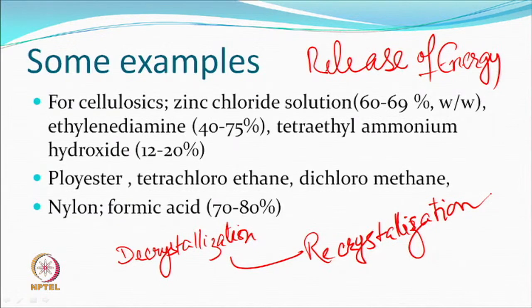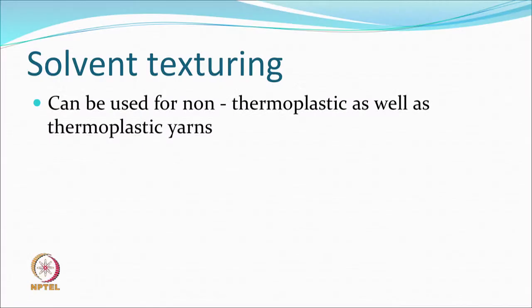If 100 percent concentration dissolves, reduce the concentration and add a non-solvent and you will find it does plasticization more than dissolution. The material must still go through the decrystallization-recrystallization process. Solvent uptake and solvent removal are analogous to heating and cooling. Solvent texturing can be used for both non-thermoplastic and thermoplastic yarns.